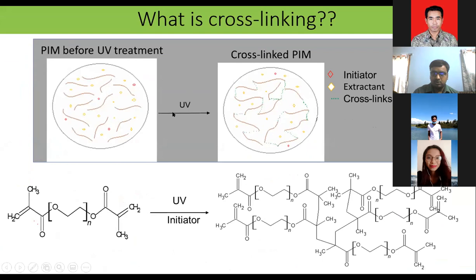And so when you put this membrane under the UV light, this initiator first breaks up, and they induce the cross-linking. So this one connects to this one, this may connect with this one. So that's how a cross-link is produced. So this is for the PEGDMA, polyethylene glycol dimethacrylate, and we are getting here the cross-link unit. So different PEGDMA units are cross-linked between each other. So that is formed within the membrane.